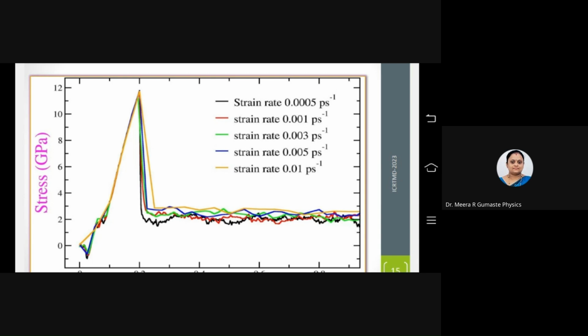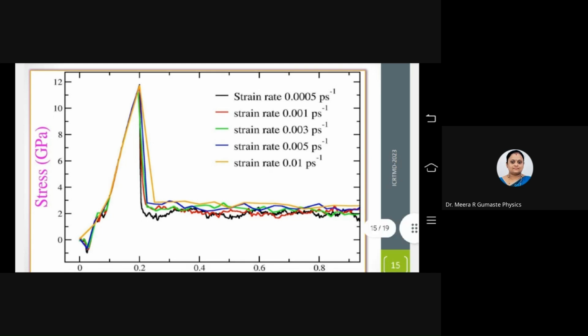So there is an elastic region. The first linear region is the elastic region. That is the elastic limit where we calculate the Young's modulus, stress by strain in that linear region. And after that there is the fracture point. The sudden fall represents the fracture point. So from this curve, the Young's modulus is calculated in the linear region by doing a straight line fitting and taking the slope of that stress by strain.